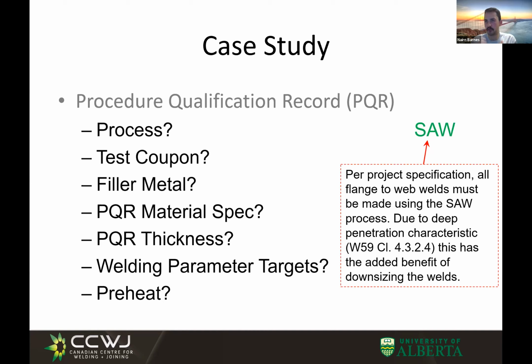So the typical weld size that's allowable in one pass for a fillet weld under most codes is 8 millimeters. Independent of the actual process, 8 millimeters is the maximum weld size you can guarantee with one pass. Beyond that, you're not allowed to do a single pass larger than that. But for sub-arc, there's this exception where, because sub-arc has this nice deep penetration characteristic from the high heat input and high amperage, you get to consider an extra 2 millimeters of penetration. So sub-arc is not only ideal because it's efficient, but if you have a 10 millimeter weld called out on a drawing, you can actually do that in one pass because you can downsize that by that extra 2 millimeters to an 8 mil weld. So sub-arc is the process we're going to use here, and that's pretty much universal for all bridge girders.